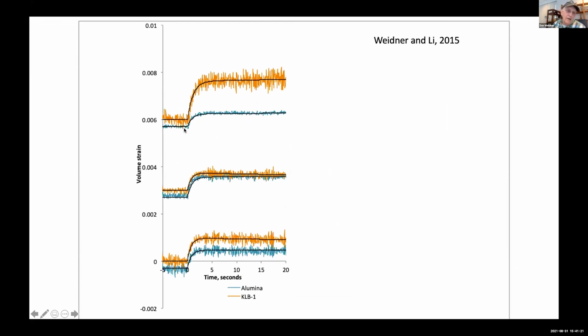which is indicated here. This is a KLB-1 sample, sitting next to it, the blue is a corundum sample. These are 3 different temperatures. There were more than this, but to make graphs simple, they're just displaced to make them look separate. The higher one, the hotter one, is above the solidus of this peridotite, and we see that the effective thermal expansion is tripled as we cross the solidus.